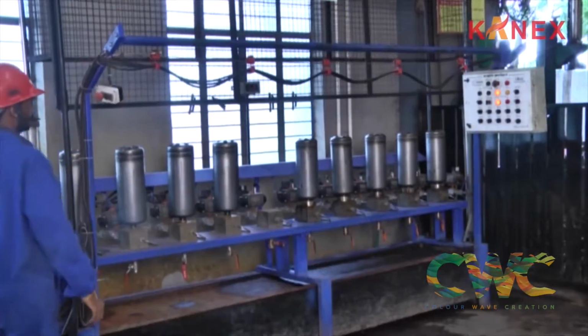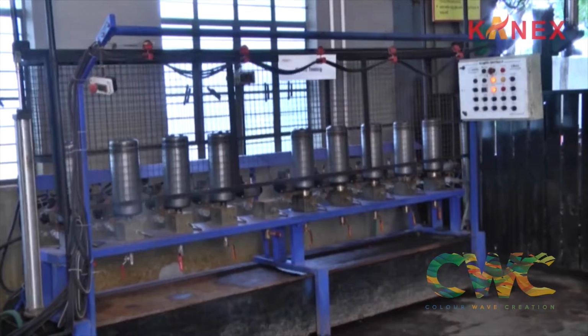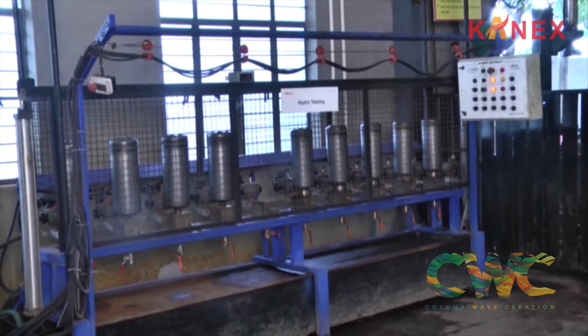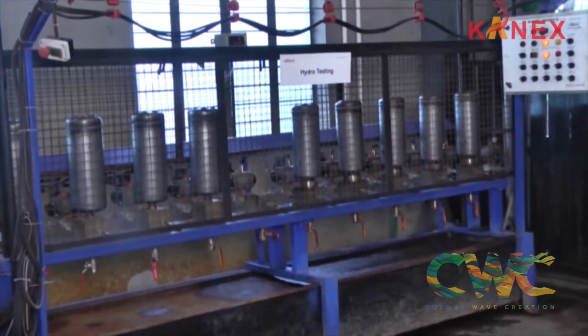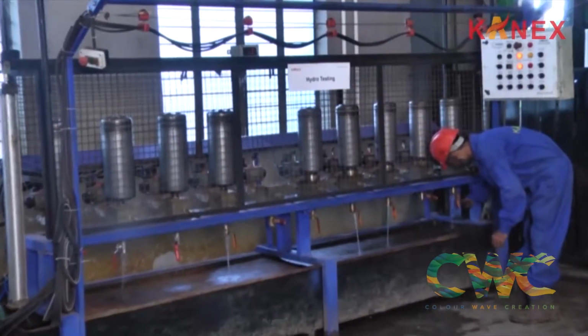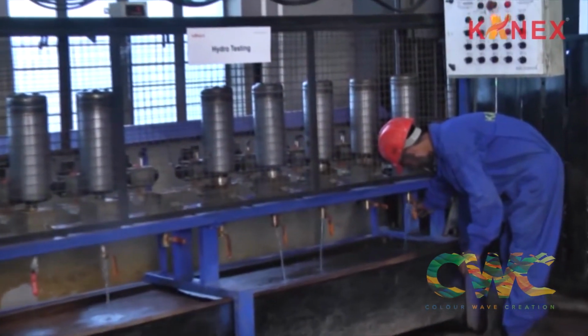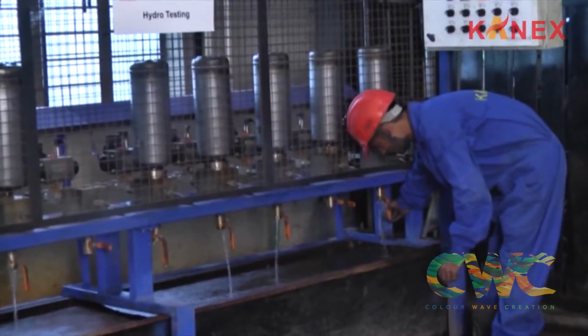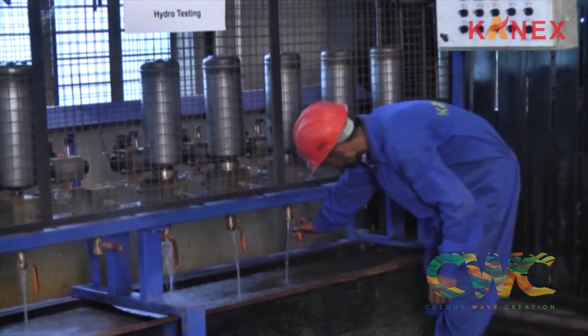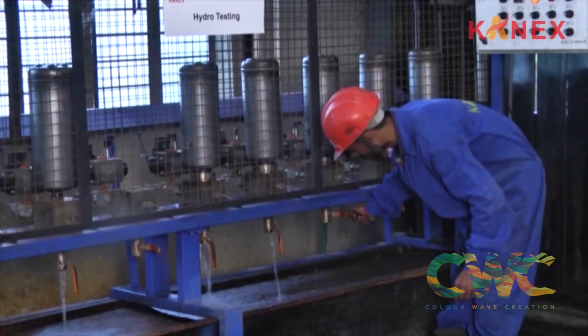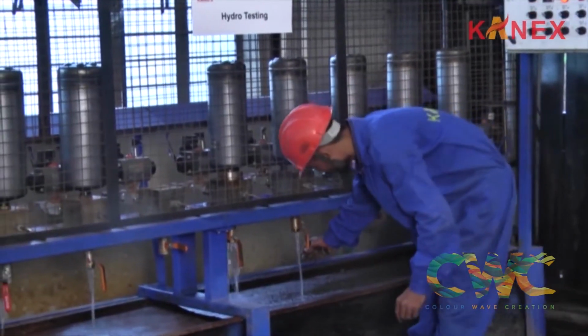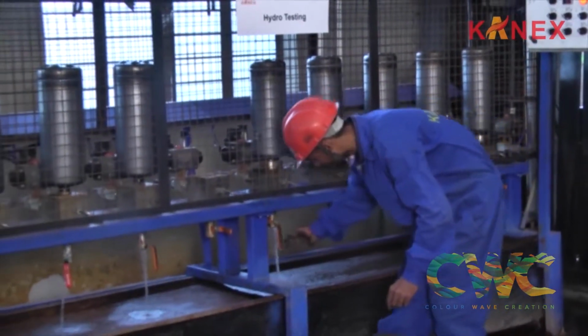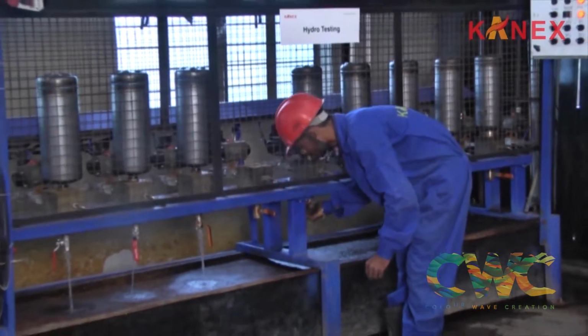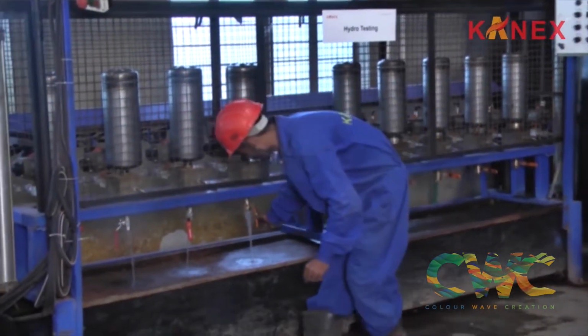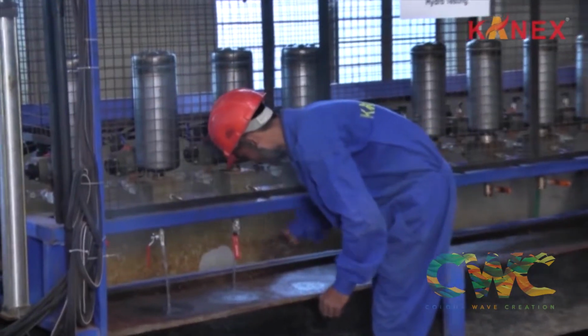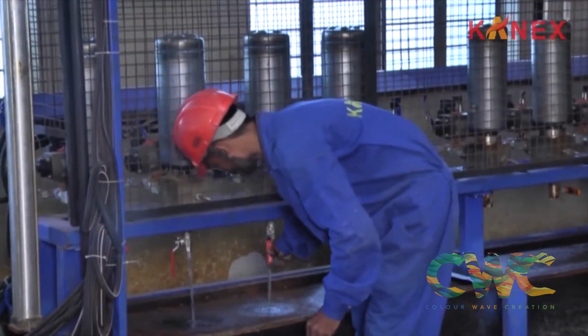The welded bodies are hydraulically tested in-house in a multiple cylinder testing fixture, which can test 10 cylinders at a time. It automatically fills the bodies with water and empties them, and then auto-generates a report of the same. The error rate is barely 0.1 bar. Pressure is tested at 35 bar. And one cylinder per lot is randomly chosen for the burst test and ultimate failure test as per standard requirement.